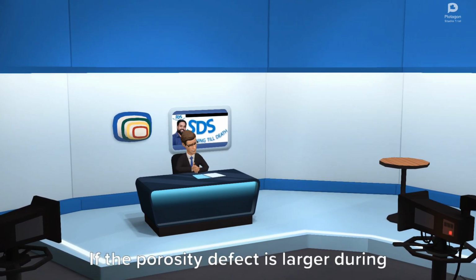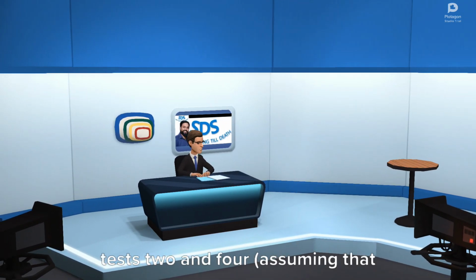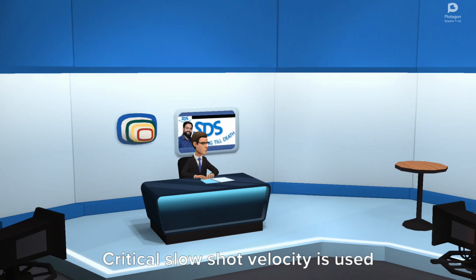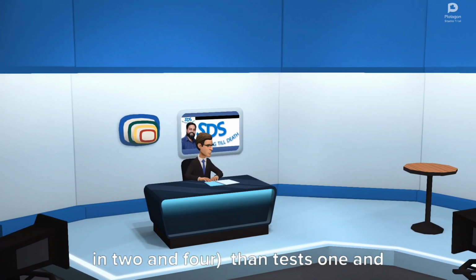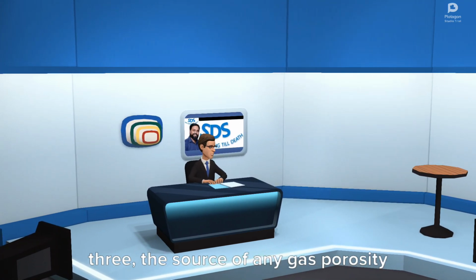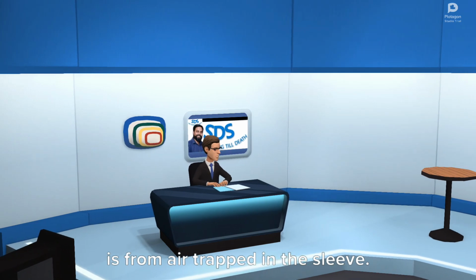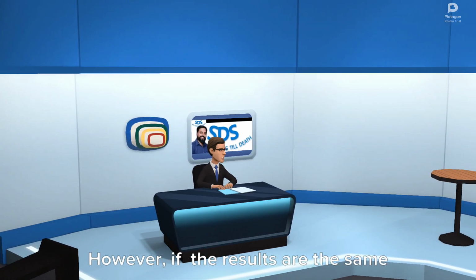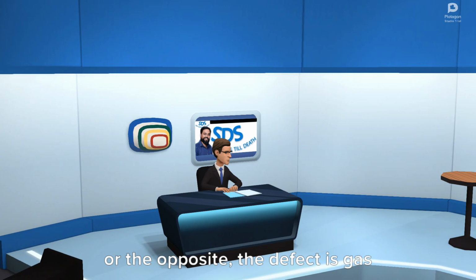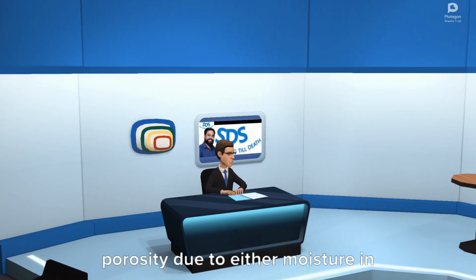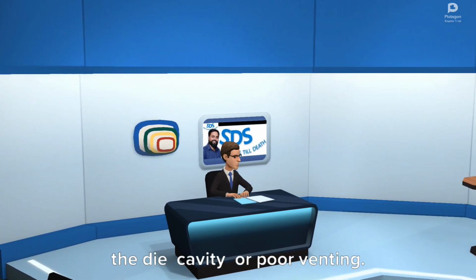If the porosity defect is larger during tests 2 and 4, assuming that critical slow shot velocity is used in 2 and 4, than tests 1 and 3, the source of any gas porosity is air trapped in the sleeve. However, if the results are the same or the opposite, the defect is gas porosity due to either moisture in the die cavity or poor venting.